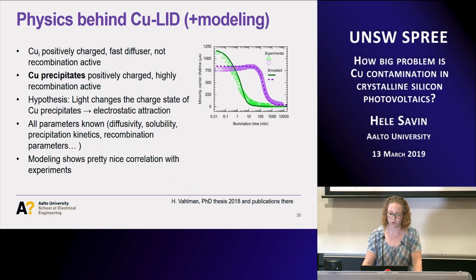If I have time, I would just want to say a few words about the physics behind the copper LID, which I haven't yet mentioned too much. Unlike all these boron oxygen LeTID theories, I think the copper theory that we have is very simple. It's well known that copper, when it's interstitial, is positively charged. It is a very fast diffuser, diffuses at room temperature, and it's not recombination active. So even though you have lots of this copper, it's not recombination active, so that's why you don't see it.